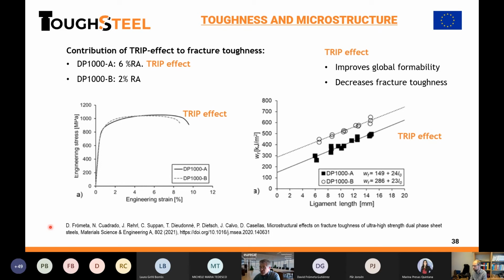So in this sense, I think that we have to look for other ways of having retained austenite. Maybe less carbon in the retained austenite, so that the martensite at the end is not that brittle, and also trying to have a more effective distribution, trying not to get the martensitic islands connected. If they are not connected, it will be more difficult for the crack to start to grow. So it's definitely a microstructural design based on the distribution and shape of martensite and austenite.